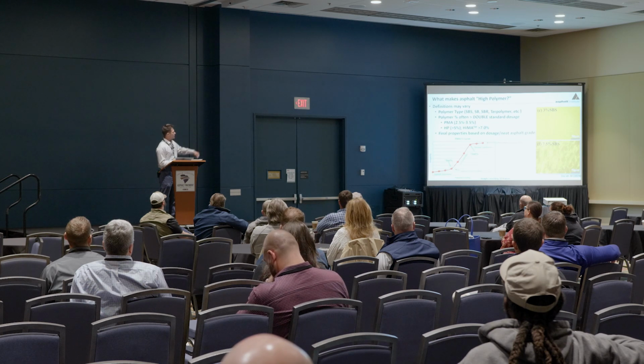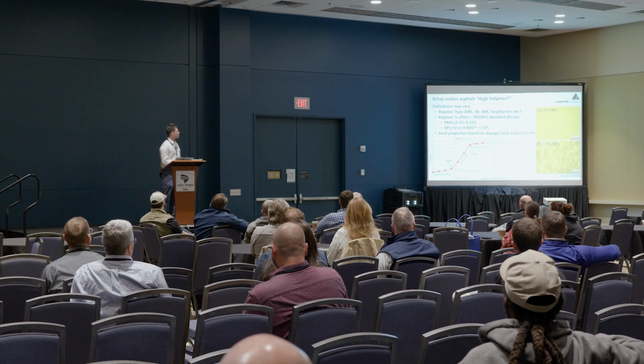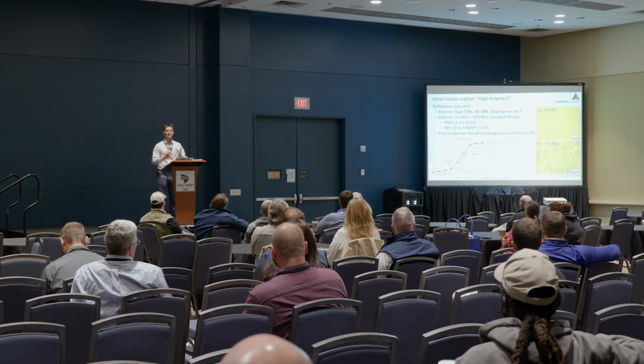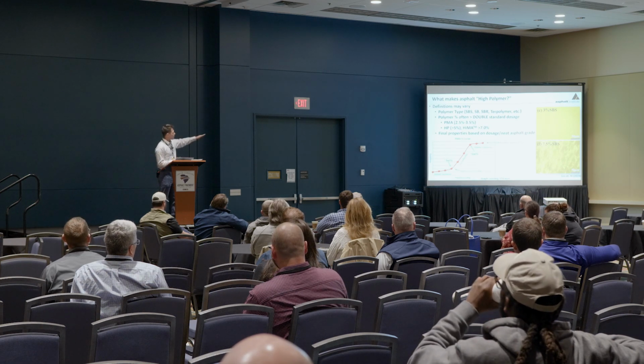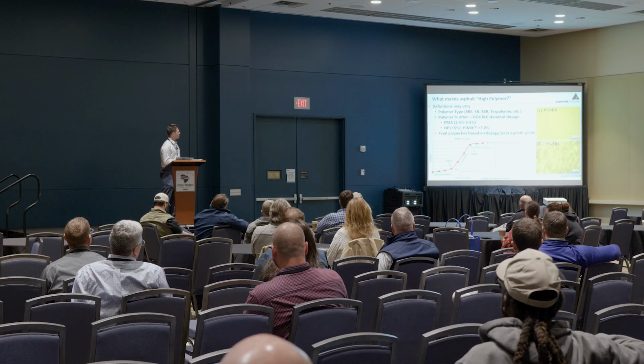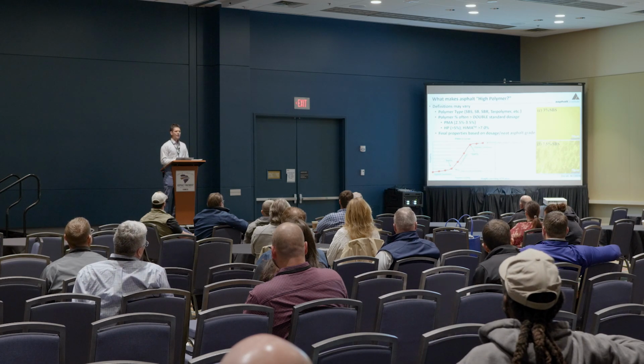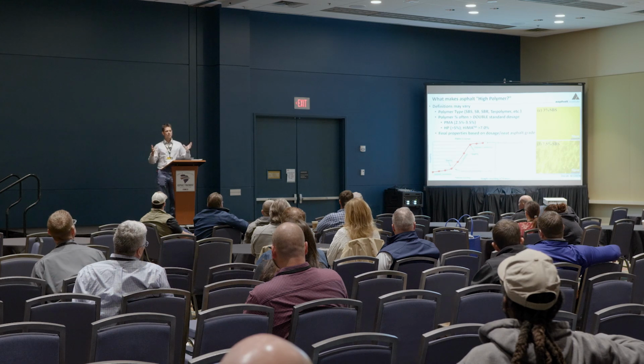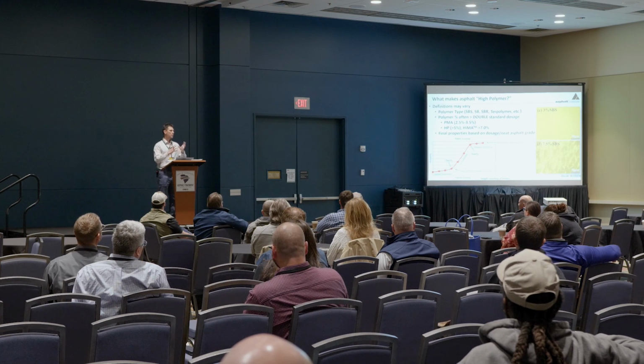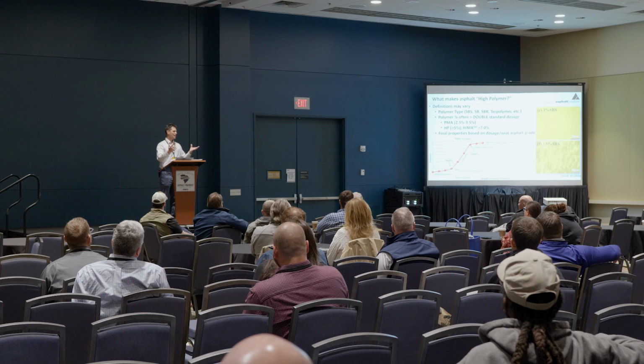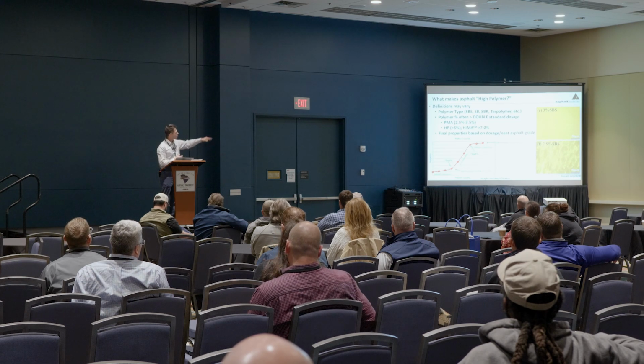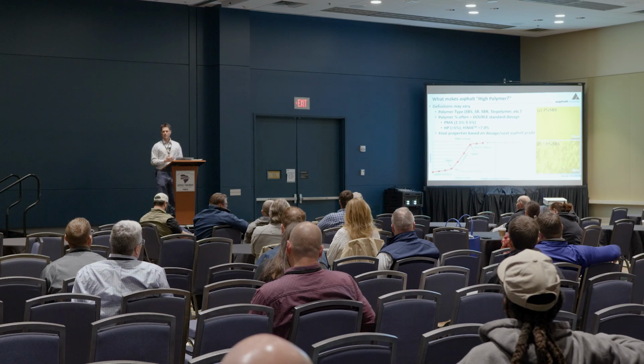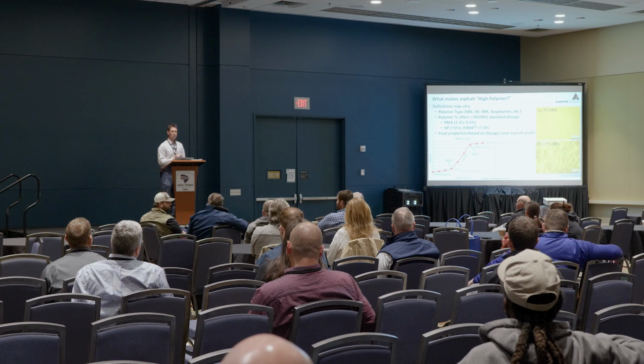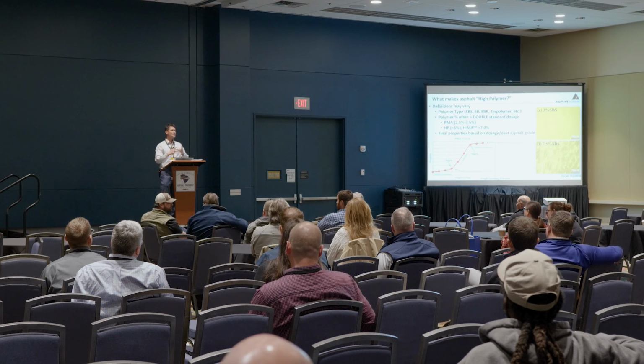Now I want to point out this S-shaped curve on the bottom. This kind of shows what happens to the asphalt polymer network at different loading rates. Where we're typically living is down here in this 2.5 to 3.5% range on the bottom. And at this point, asphalt is the dominant phase. And the polymer network is within the asphalt, but asphalt is still the dominant phase. And as you move up this S-shaped curve and get above about 6% on the polymer dosage, there's a transition that takes place where, although that polymer is only there at 6% plus, the polymer begins to become the dominant phase.